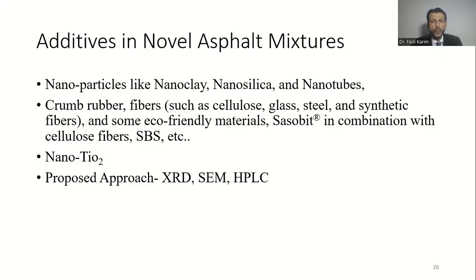In order to improve the performance of asphalt cement, the nanoclay is used as per dry method, and the crumb rubber I use as per wet method. Both of them are used to improve performance of asphalt mixture. But here, I would like to describe that sometimes it is very difficult to detect the distribution or the presence of nanoclay or crumb rubber in the asphalt cement or asphalt mixture during micro level study. It's very difficult to detect.